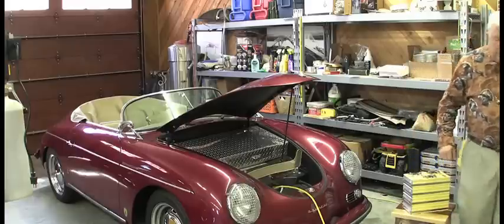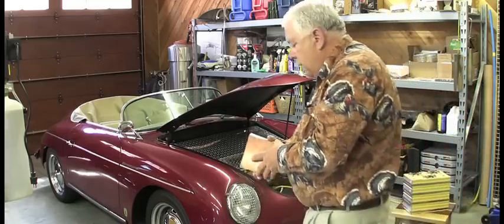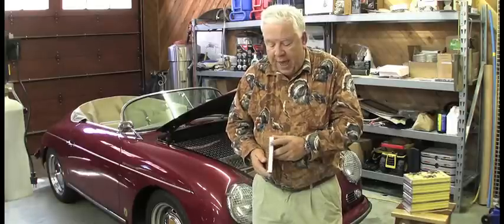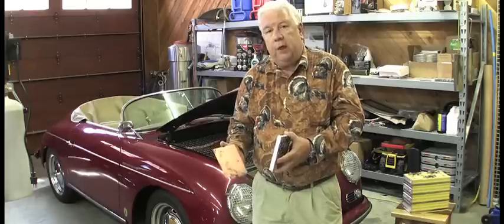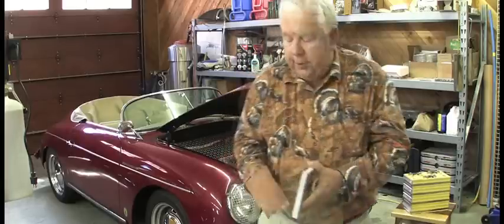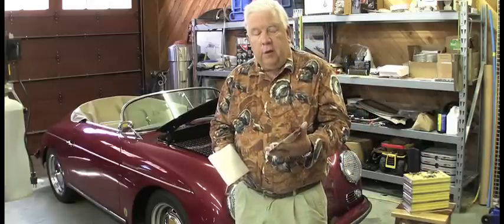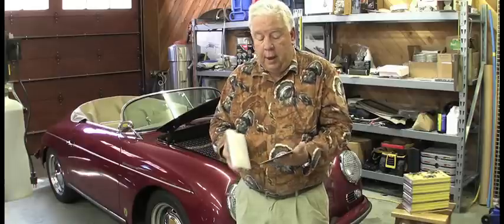Let's talk a little bit about the basics of the battery. I've made kind of a sandwich here. This is a piece of copper plate, this is a piece of aluminum plate, and this is simply a piece of foam. Actually, 90 percent of the battery is copper foil and aluminum foil. They take the copper foil and on both sides of it smear a slurry — a paste of nano carbon fiber particles and graphite. That's going to form our anode or negative terminal of the battery. The aluminum foil is similarly covered with a slurry on both sides, a paste of lithium iron phosphate. That's the technology currently being used by ThunderSky.